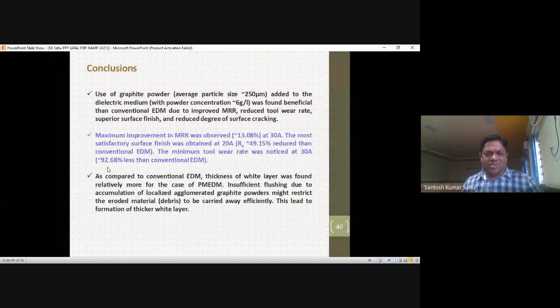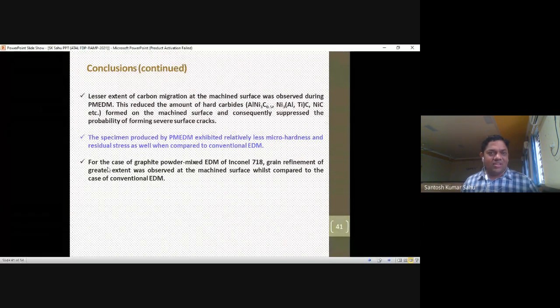As compared to conventional EDM, the thickness of the white layer is found relatively more in the case of powder mix EDM, because of insufficient flushing due to localized agglomeration of the graphite powder, which might restrict the eroded material or debris from being carried out efficiently, and this leads to an increased white layer thickness. To a lesser extent, carbon migration can occur during powder mix EDM, which reduces the hard carbide layer formed on the machined surface, and that consequently suppresses the potential for formation of severe cracks. This hardness can also be minimized by adding powder in EDM, because this hardness is the cause of cracks.